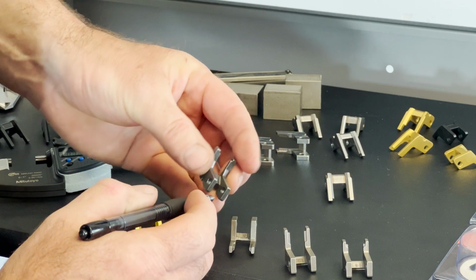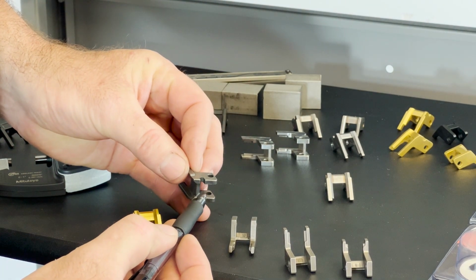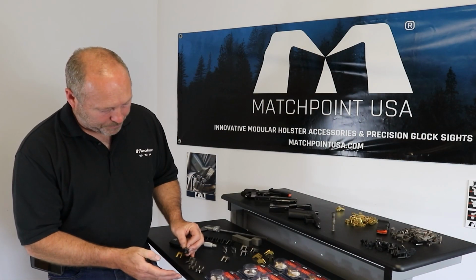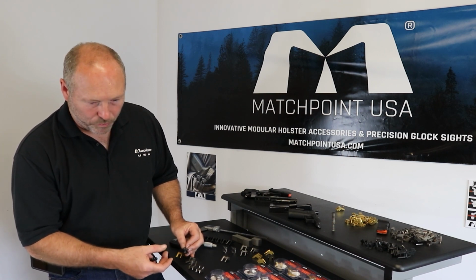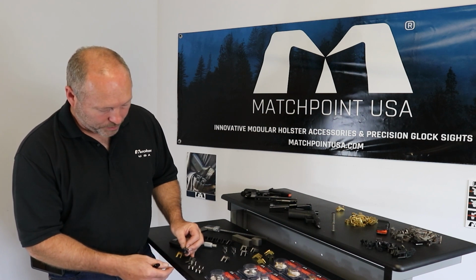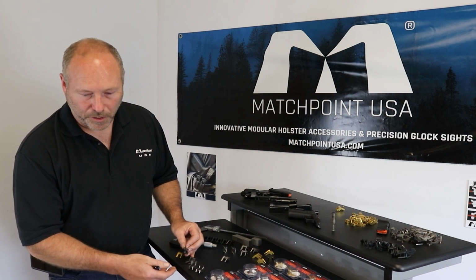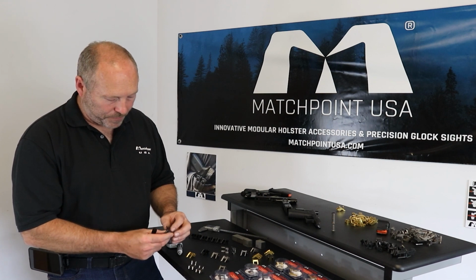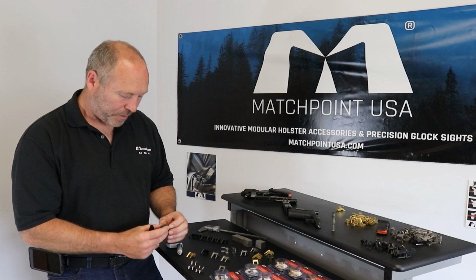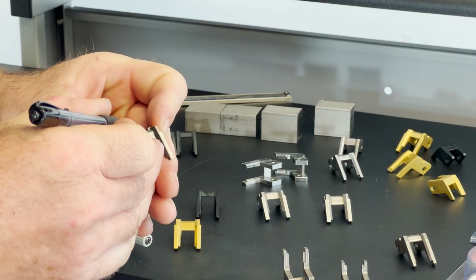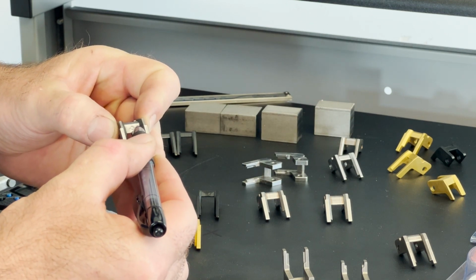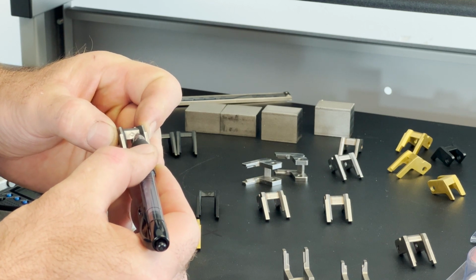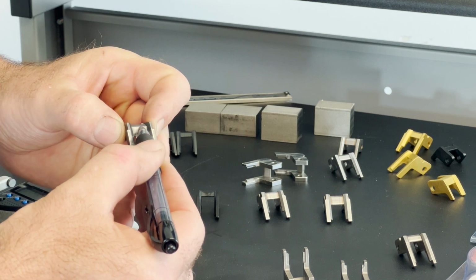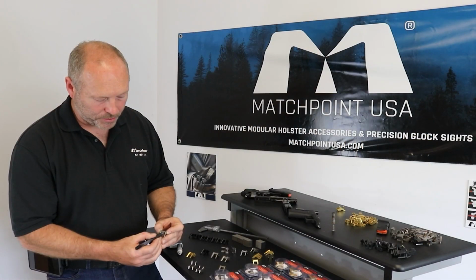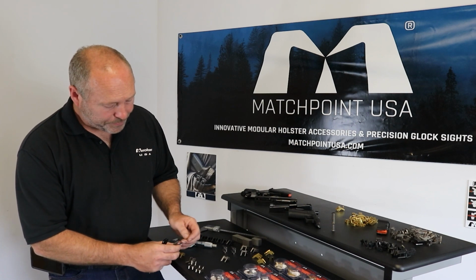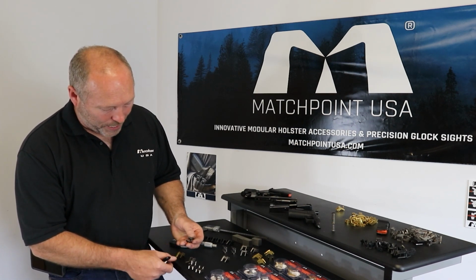There's some slides inside. I don't know if you can see that, but you can see that square on the inside. And what happens on slides is they're not returning to the same position as that mold when it was manufactured. It was probably pretty smooth, but over time the molds tend to wear out, the tooling wears out, and you start gaining more and more variables. One of the problems that the sintering process creates is differential shrinkage. Differential shrinkage is if I look at this feature, for example, as it moves closer to the edge where the heat gets sucked out of it, it would have a tendency to shrink more in that area. It's the last place that's hot, so the center would cool first, and as the part shrinks and cools, it moves.